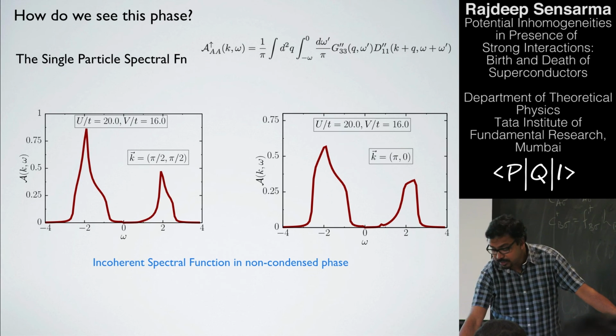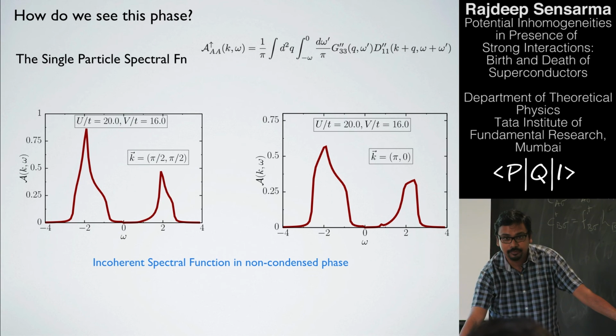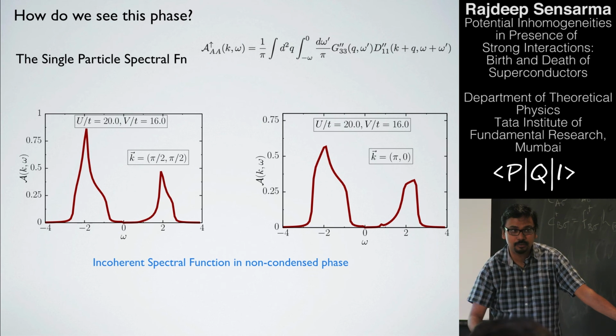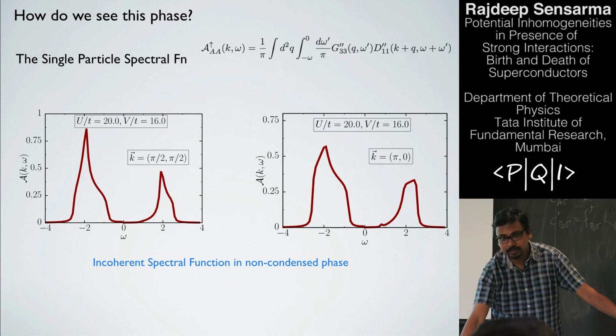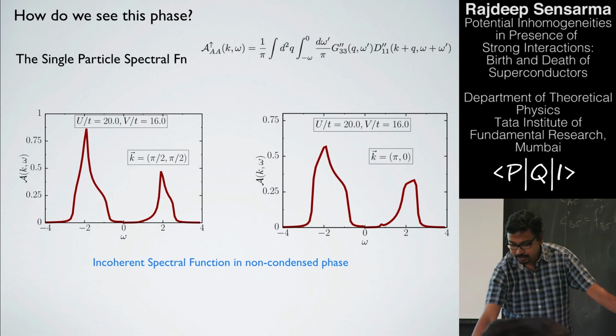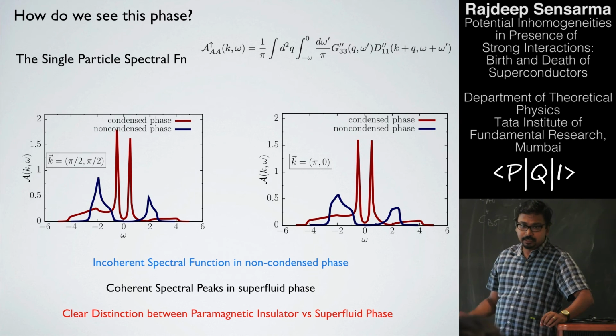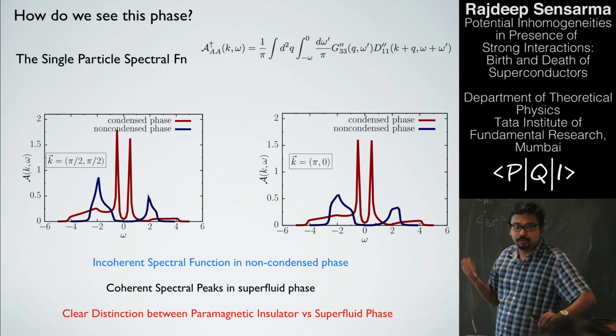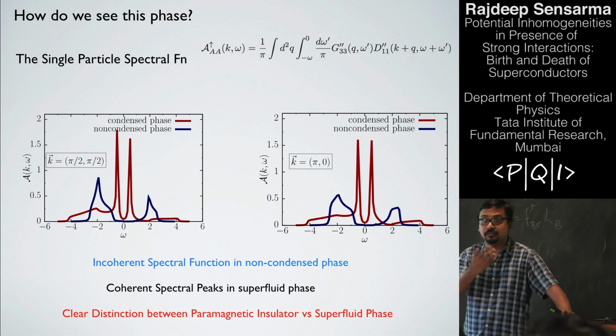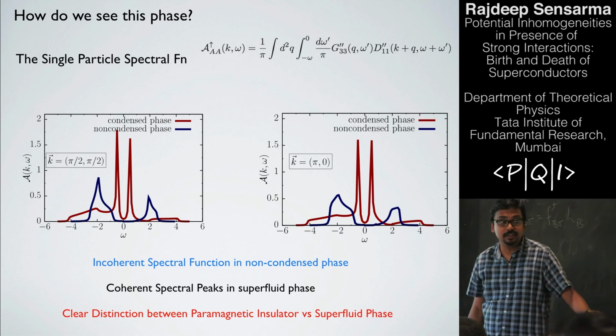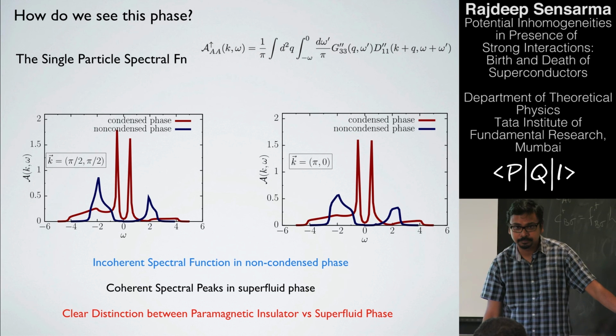Okay, so if you measure the single particle spectral function, what you see is that in the paramagnetic phase, you have gapped but very incoherent spectral weight. There are no nice quasi-particles sitting there. Whereas as soon as you go superconducting, the condensate forces you to have very sharp quasi-particle peaks. So this could be one way you can distinguish these two phases.